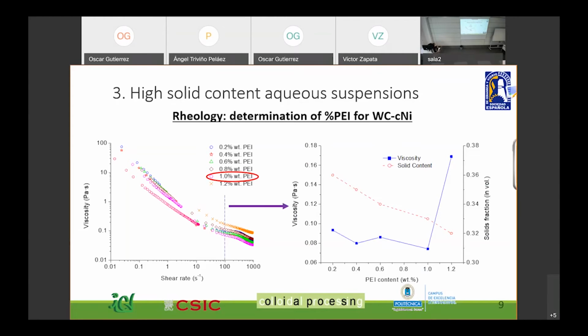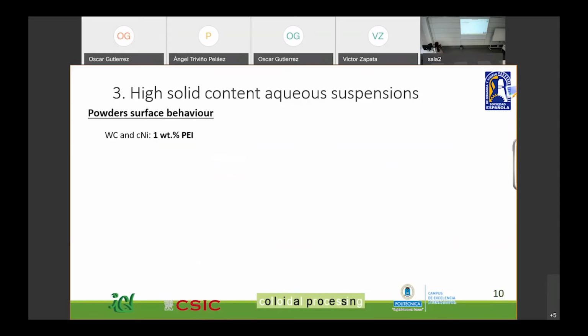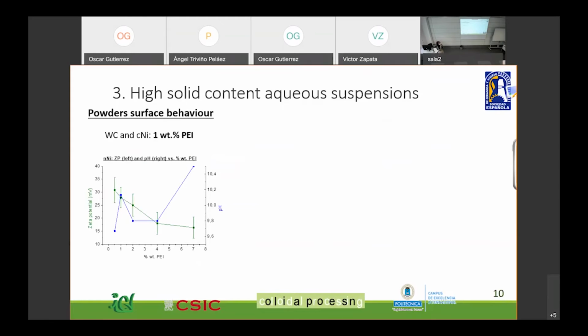And from that point on, the viscosity of our suspension just shoots up, which is not very desirable for our suspension preparation. After that, we decided to confirm this data with some powder surface behavior studies by measuring the zeta potential of our particles in suspension. When the value of the zeta potential stabilizes and just remains constant, we would say we found the optimal amount of dispersant for our formulations.